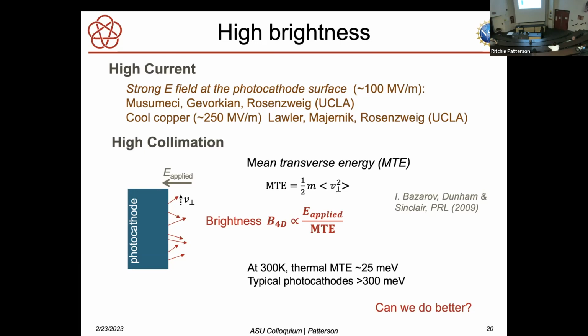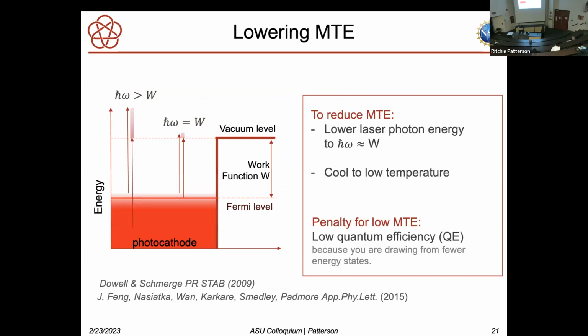At room temperature, you've got thermal mean transverse energy of about 25 millielectron volts. It turns out that typical photocathodes today, like copper, will operate with more than 300 millielectron volts, so far above what you would expect from thermal effects alone. And the question is, can we do better than that? And so maybe we have to think just a little bit about the photoemission process. And so we have this energy diagram, and here's the photocathode. Energy levels are filled up to the Fermi level. And then to emit an electron, you need to supply a photon that has at least this work function in order to kick the electron out into the vacuum.